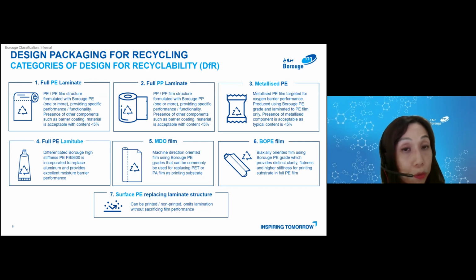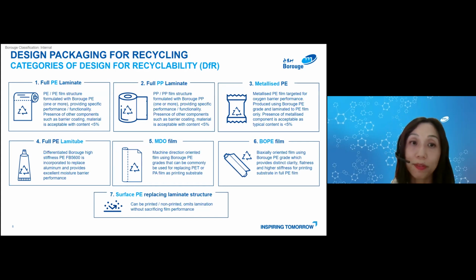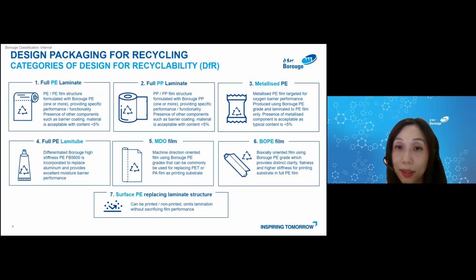There is also the full PE lami tube for applications like toothpaste, where differentiated Borouge high stiffness FB5600 replaces aluminum and provides excellent moisture barrier performance. And over here, number 5, we have MDO film, which is another hot trending topic in the monomaterial space. And Borouge PE grades can be used for replacing PET or PA film as a printing substrate. Another fast developing area is in BOPE, using Borouge PE grade, which provides distinct clarity, flatness, and high stiffness for printing substrate in the full PE film.